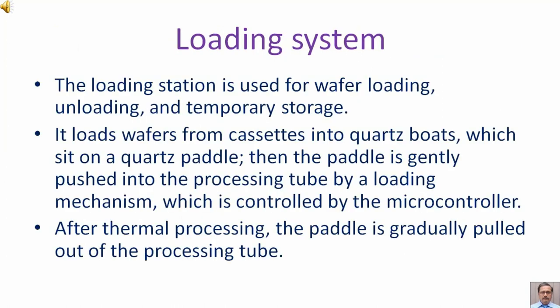Loading system. The loading station is used for wafer loading, unloading, and temporary storage. It loads wafers from cassettes into quartz boats which sit on a quartz paddle. Then the paddle is gently pushed into the processing tube by a loading mechanism which is controlled by the microcontroller. After thermal processing, the paddle is gradually pulled out of the processing tube.